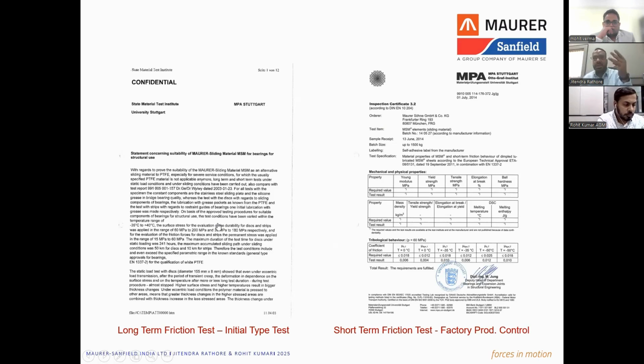And the third is the temperature. The temperature of this test specimen is changed from minus 50 degrees centigrade to plus 70, then coming back to minus 50, then going to plus 70. So all these three parameters are changing in a cyclic or sinusoidal way, and the specimen is tested for 50,000 meters of sliding. And then it should not result in a loss of the material thickness by more than a certain millimeter. So that is not the entire, but one of the several tests that are to be done to make this material qualified.